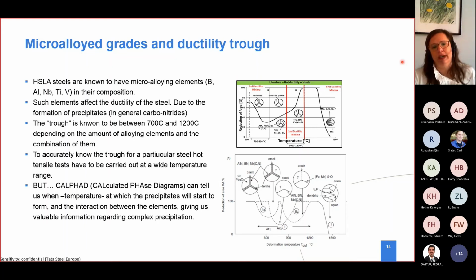We know that high strength, low alloy steels are steels known to have microalloyed elements. Why micro? Because they are alloyed in a very small amount, so micro scale. Sometimes it's boron, for example, at the levels of ppm. So they have very, very little amount of these elements in the composition. But this very small amount of elements broadly affects the ductility of the steel.